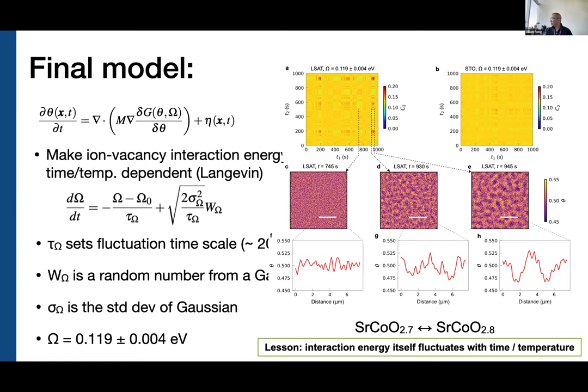Later on at 930 seconds, you can see that for the film grown on LSAT, there's now some phase separation. You can see that by the larger change in the oxygen concentration as a function of distance. Now you can see some peaks and valleys that correspond to real phase separation. Same thing for 945 seconds. But again, for the same parameters on strontium titanate, the elastic term dominates, so you see no fluctuations in your two-time correlation.